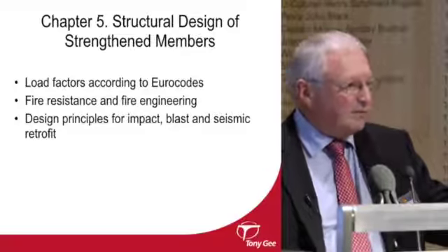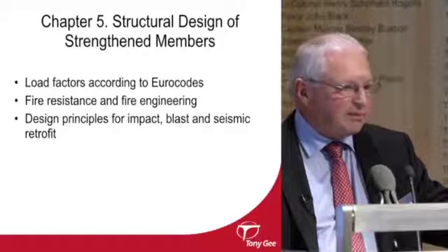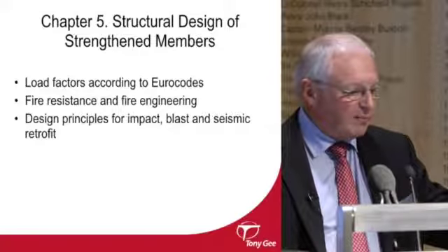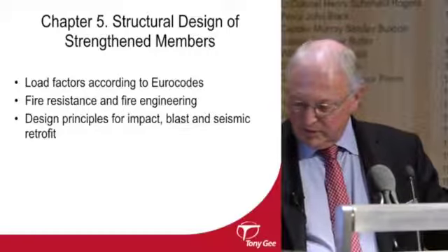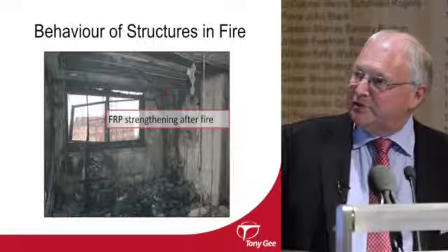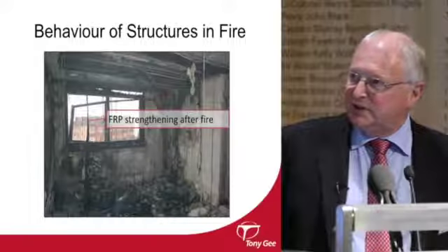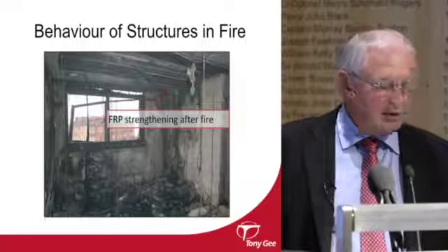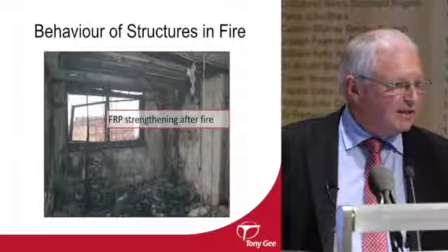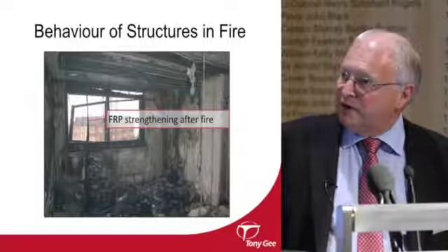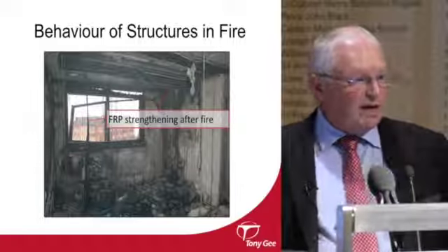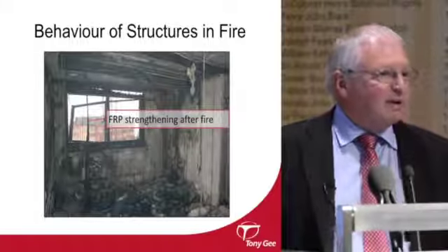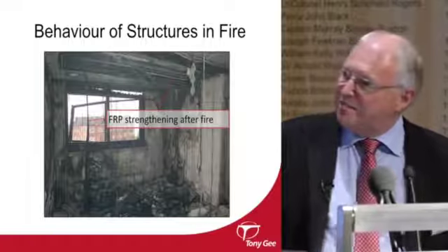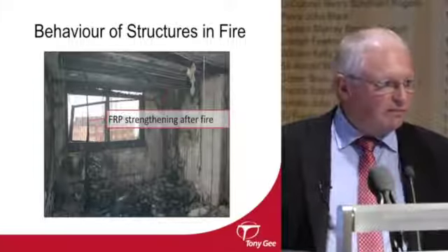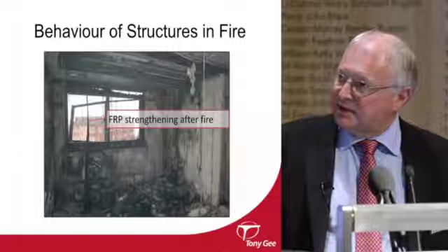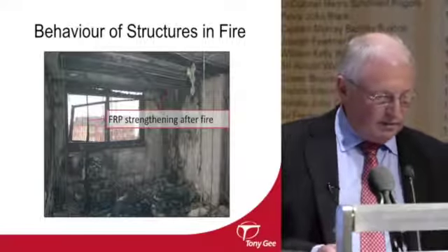If you leave things long enough, you'll start to gain experience. Things will happen to structures, and we've had some real fires in FRP strengthened structures. So we now know what we knew from the laboratory, that if you're up well beyond 300 degrees C, then by and large the resin is going to decompose, and therefore the strip is going to become ineffective. Your loading may also be lower, almost certainly will be, because some of it might even have been burnt away. So you can use reduction factors in these situations, but you do have to be a bit careful in the fire situation.